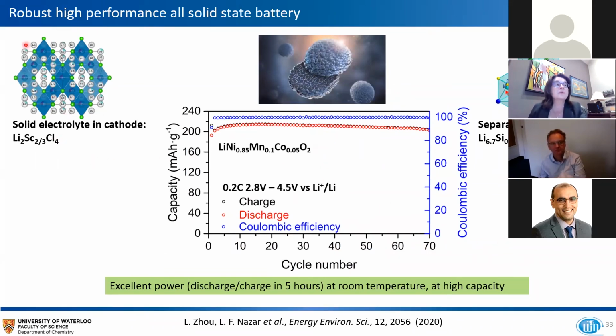So again, this is our best halide. This is the one that seems to work the best. We're using this material as the separator. We've coated our materials by a very simple ball milling procedure, actually hand grinding, quite honestly. And so we're able to achieve excellent power because the cell can be discharged and charged in 5 hours at room temperature. And best of all, we get capacities in terms of milliamp hours per gram that are equivalent to its liquid lithium ion counterpart. So we think this is definitely a step in the right direction, and we can sustain charging up to 4.5 volts without coating the cathode material at all. So this is a bare naked cathode material simply with the halide on the surface, and a typical solid electrolyte as a separator.